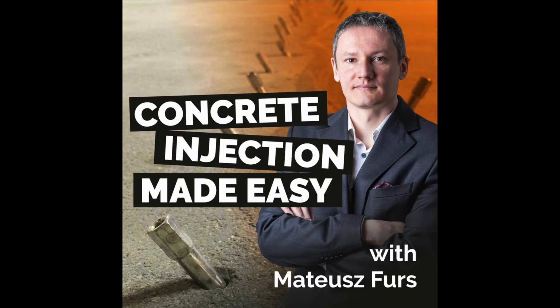That's also the mistake people sometimes make. They use one kind of product for all the jobs, and then they say, oh, it's not working here, but it's not working because from the beginning the product chosen was not a good one. To have really low shrinkage, really low swelling, and a low drying phase, you have another alternative, a derivative of acrylic: methacrylic. Using this kind, you have nearly no drying.